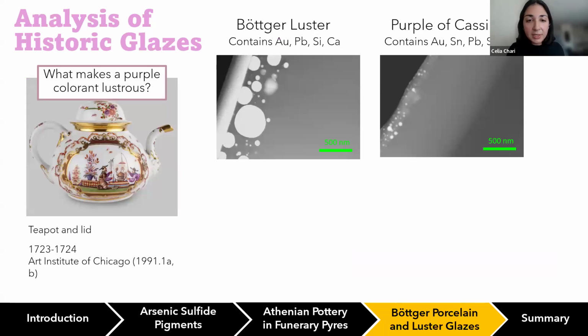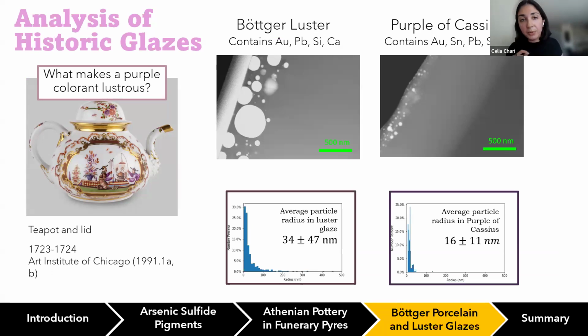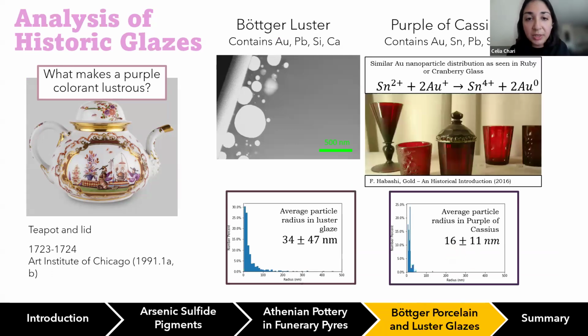So we carried out some statistical analyses to see the distribution of nanoparticle sizes in both the luster glaze and in purple of Cassius. And we can see that with purple of Cassius, the nanoparticle size is really uniform. And this size that we're seeing on average is really similar to the nanoparticles that we would expect to see in ruby or cranberry glass. So these historic glasses are essentially colloids of gold nanoparticles within a tin-rich matrix. And they're prepared by mixing gold salts with tin that acts as a reducing agent, allowing for those gold metal nanoparticles to nucleate and grow. And in a similar way, purple of Cassius might have been synthesized and prepared using tin as a reducing agent, which could explain why we're seeing such a localized presence of tin directly surrounding those gold nanoparticles.